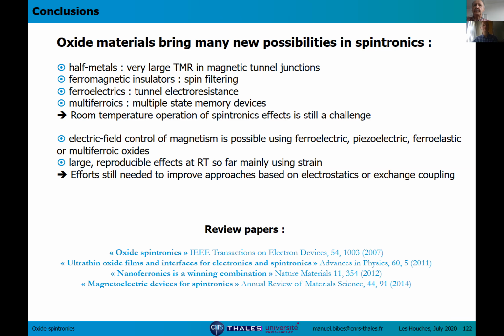When you combine these two effects using multiferroics as tunnel barriers, you can have multiple state devices. But this is still a challenge to have this at room temperature. I've shown you 3 approaches to control magnetism with electric field: strain, field effect, and exchange coupling. And I think there's a number of interesting results in each, but to me, the most promising is the last one using bismuth ferrite from the work of Ramesh.